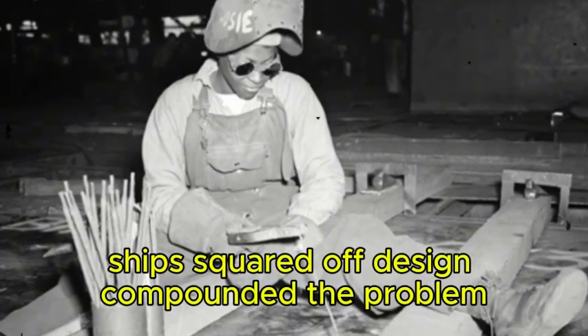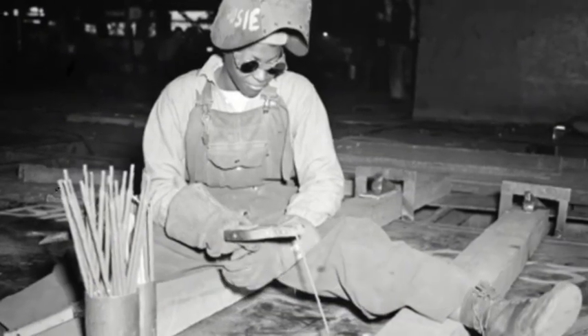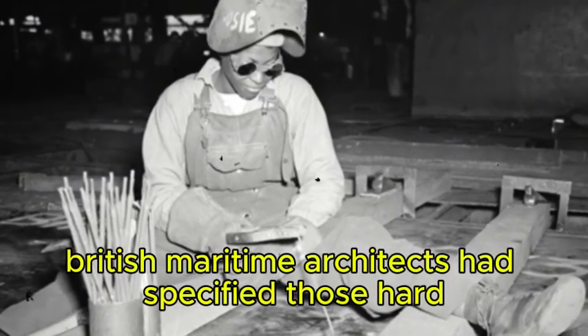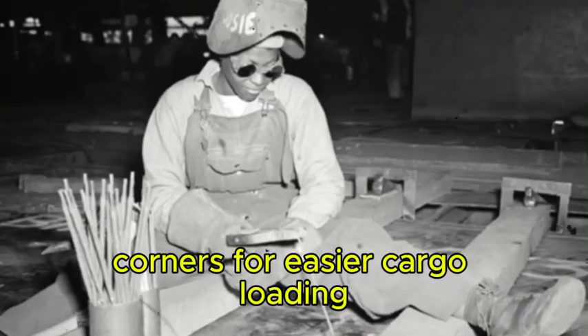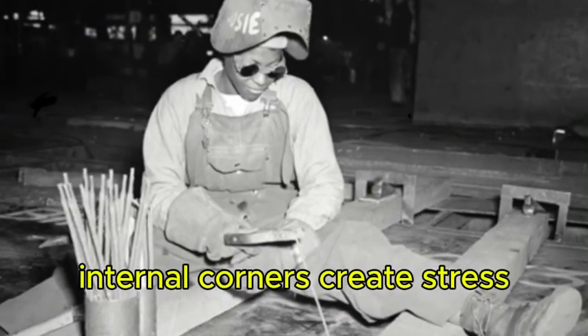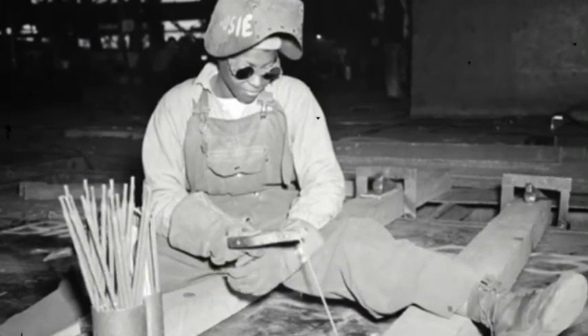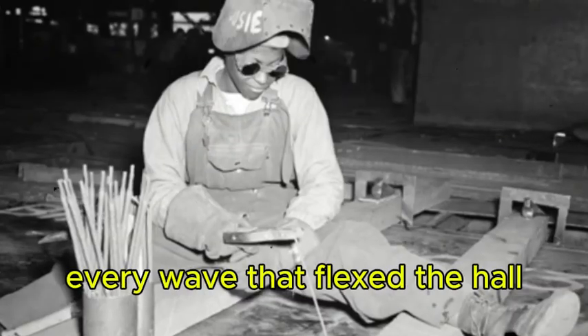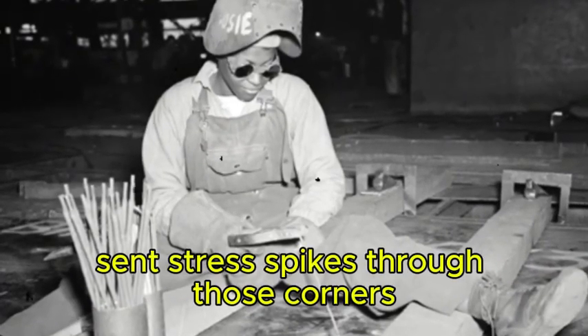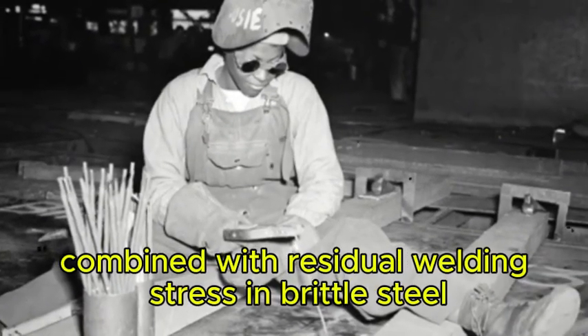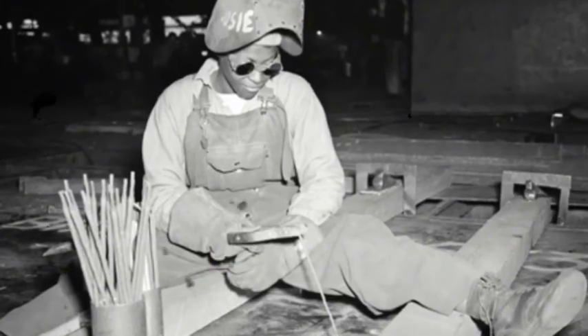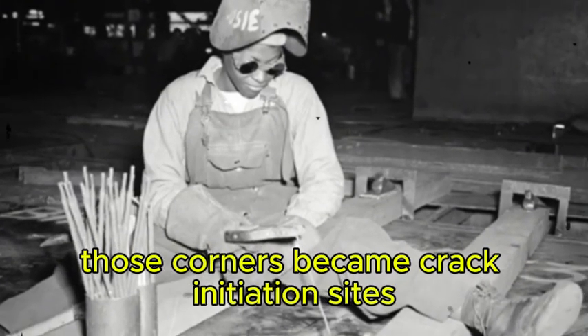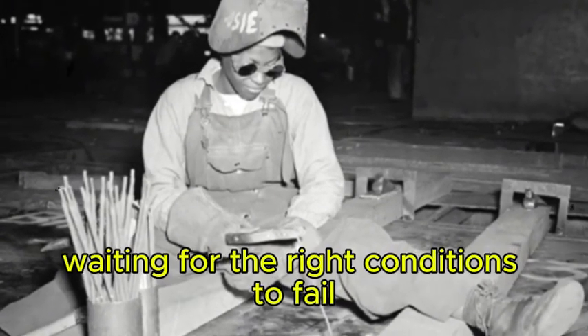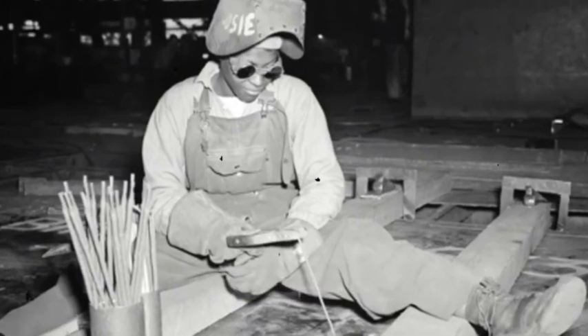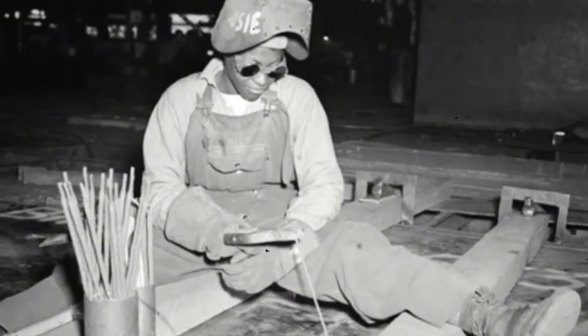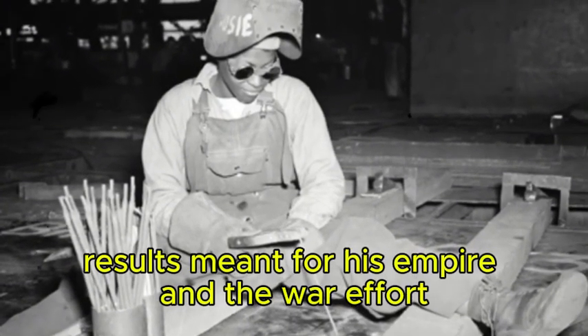The Liberty ship's squared-off design compounded the problem. British maritime architects had specified those hard corners for easier cargo loading. Nobody considered that sharp internal corners create stress concentrations that multiply applied loads by huge factors. Every wave that flexed the hull sent stress spikes through those corners. Combined with residual welding stress and brittle steel, those corners became crack initiation sites, waiting for the right conditions to fail catastrophically. Henry Kaiser understood what the test results meant for his empire and the war effort.